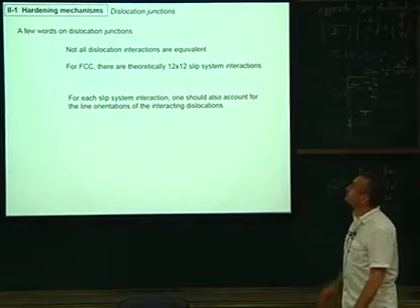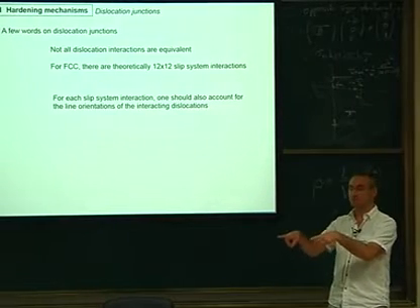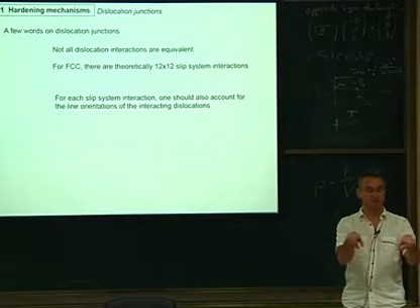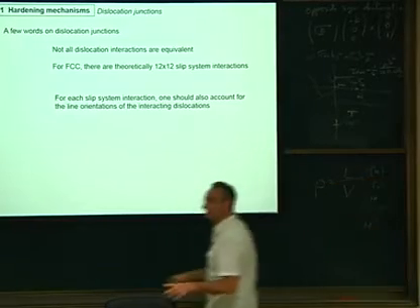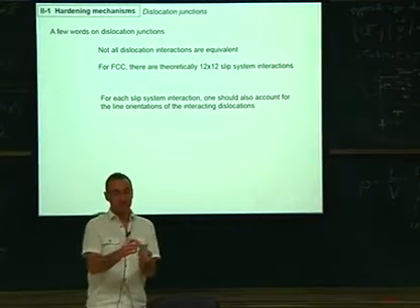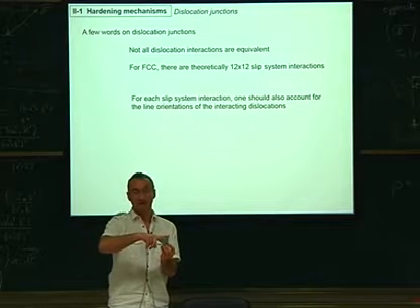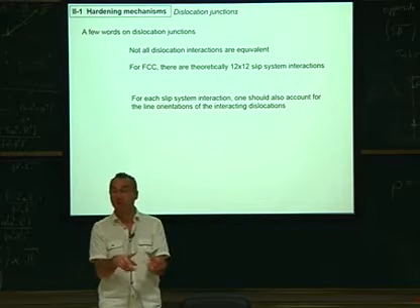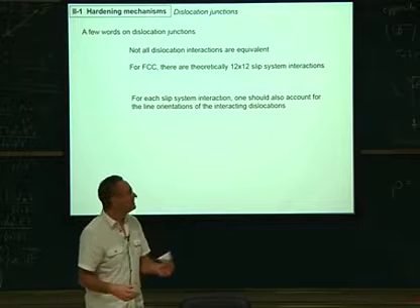Because actually not all dislocations are the same. If you put two dislocations in the same plane, typically you see that they don't form a forest. There is no forest hardening between two coplanar dislocations. And we saw in the Thompson tetrahedron that in a given slip plane, you have 3 slip systems. So typically you may move that dislocation and that one, so they do not form a forest. It will be more like a junction, but not a forest, you see. So it's not so easy.